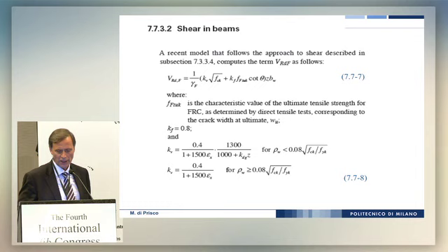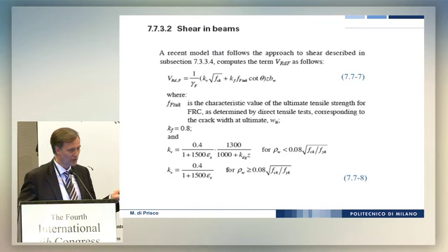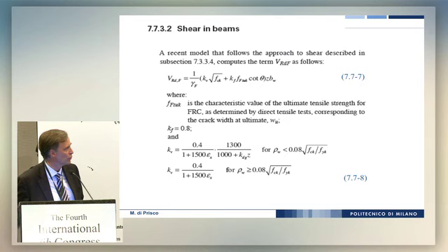We introduce some equations related to shear. Shear is very important because in a lot of situations you are forced to introduce transversal reinforcement, and with fibers you can prevent the introduction of this. And for this reason, we introduce essentially this equation where you find the contribution of fibers essentially at this point, and of course it is coherent with the theory already illustrated by Professor Muttoni and Professor Sigrist.